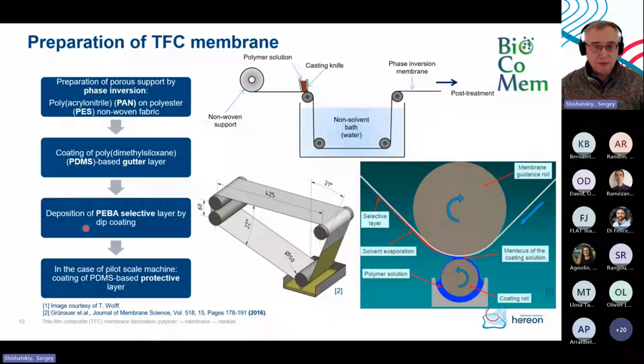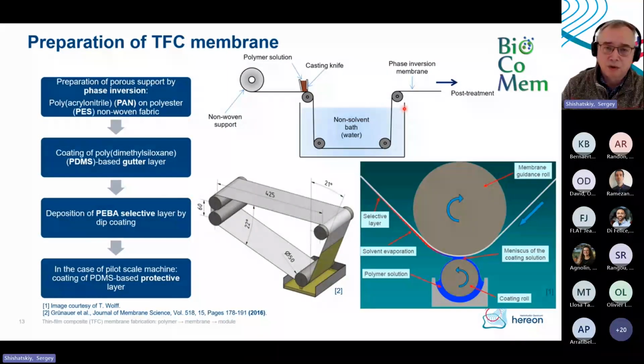So how is a membrane formed? At first we need to produce a porous support. It's done by standard solvent-induced or non-solvent-induced phase separation. You cast a thin layer of a polymer solution onto the non-woven, and then you dive it into the quenching bath, and the phase inversion process occurs, and then you collect it and send it to the post-treatment. Then when you have this support, you start to deposit layers on top of it.